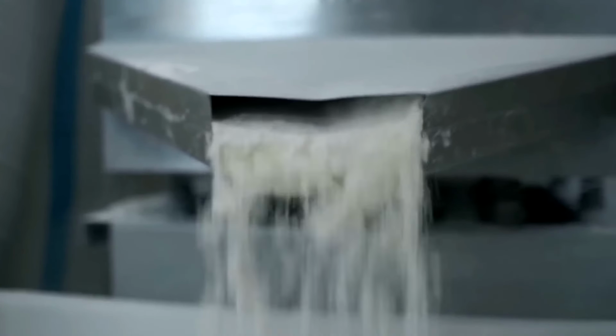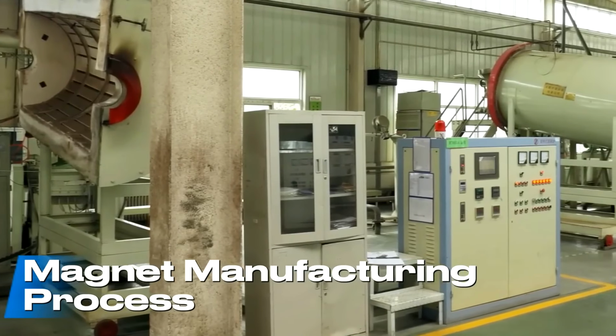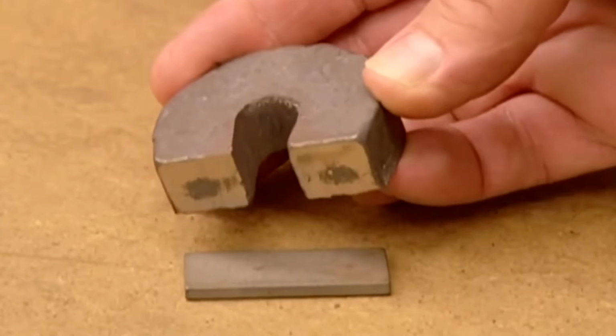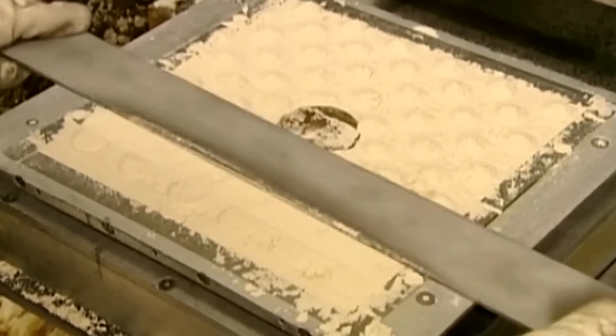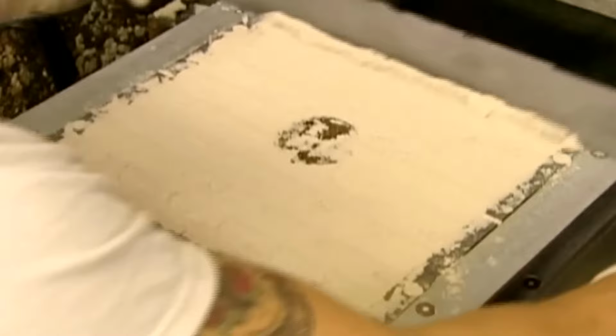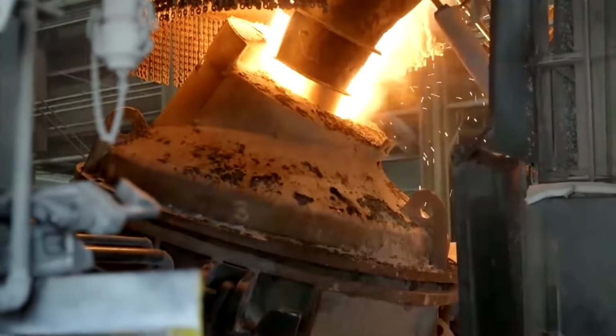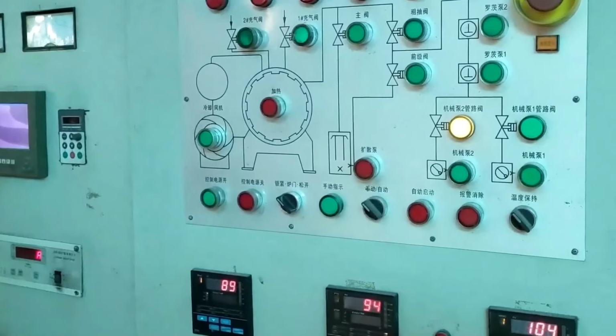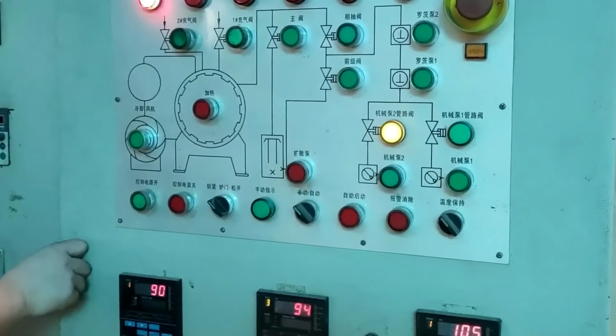With the metals now fully molten, the alloy is quenched in an instant. It cascades onto a rapidly rotating drum where the liquid metal solidifies into thin metallic flakes within a few seconds. This technique of instantaneous cooling freezes the material into a fine and uniform crystal structure.